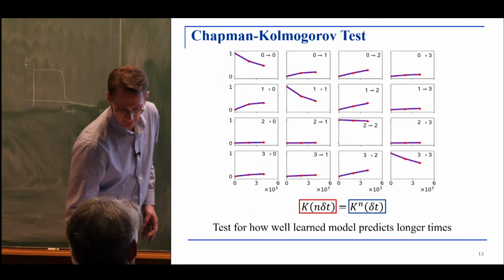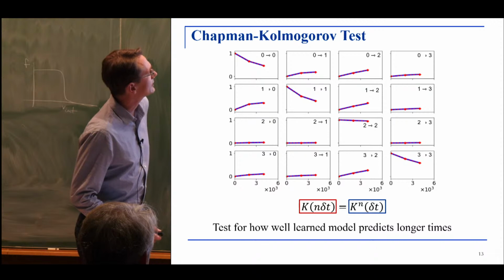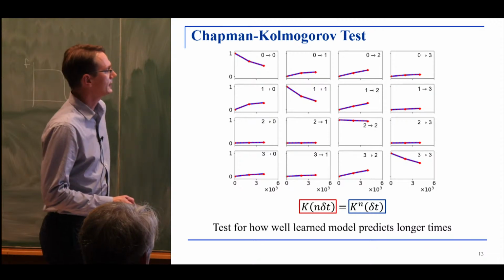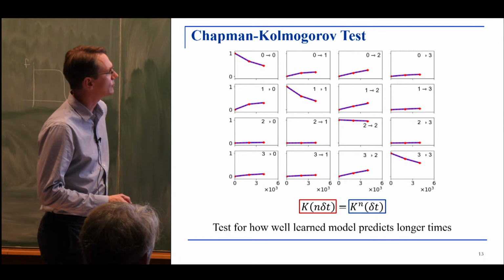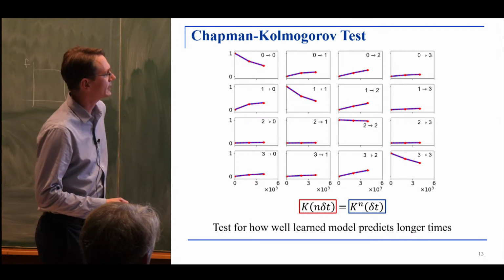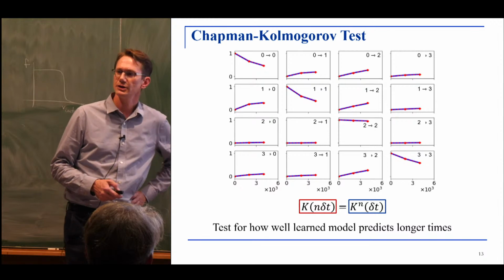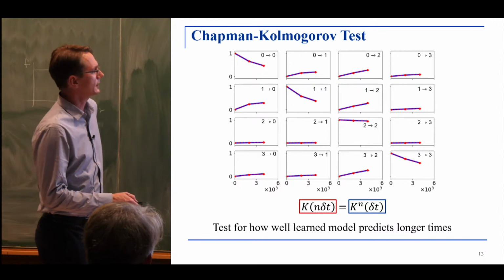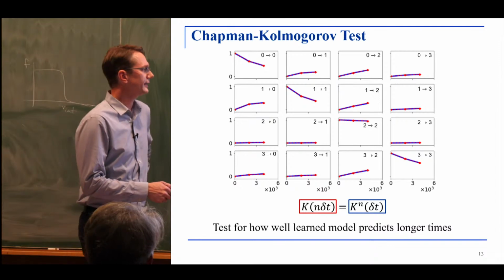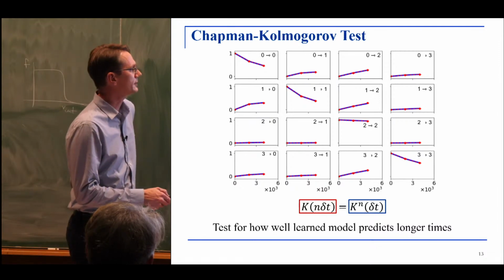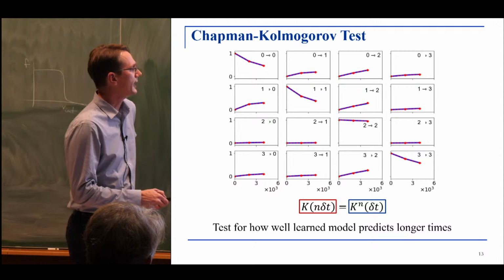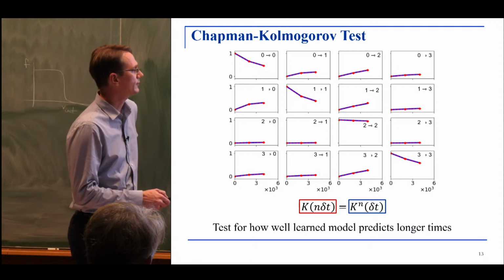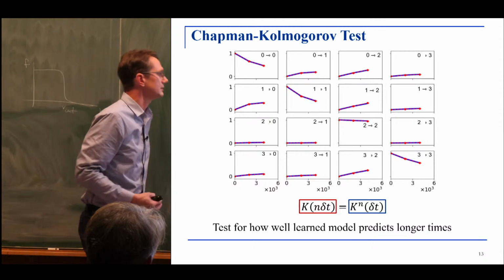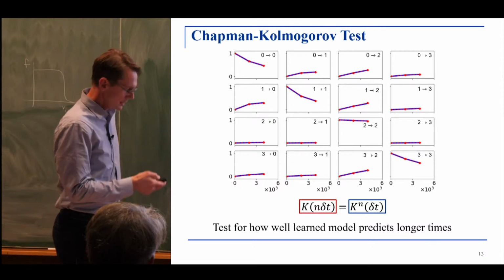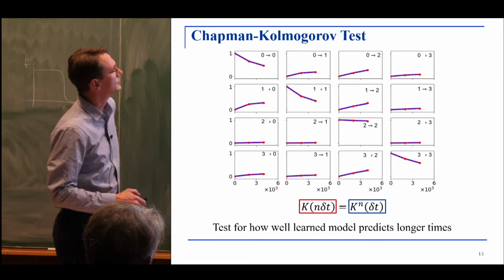Now the next step, maybe I show this real quick, is to check how well the learned model predicts longer times. The Markov state community calls this a Chapman-Kolmogorov test. Essentially, if the dynamics is linear, then if you apply the propagator n times, you should get the same result as just observing the system n times the lag time. And indeed, this works out quite well for the different transitions that occur in the model. So this is a sanity check that the model does make sense.